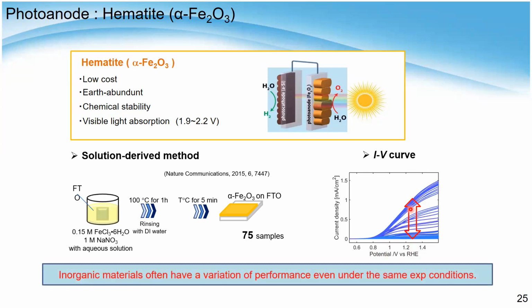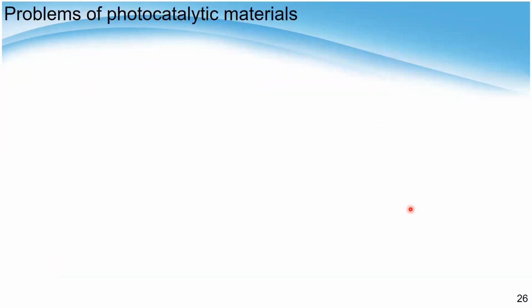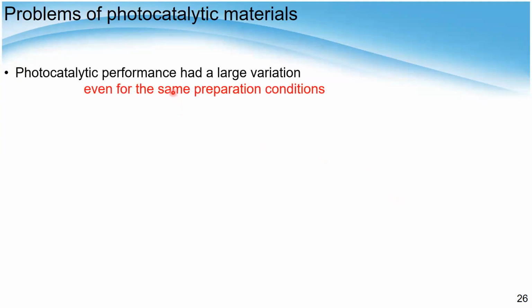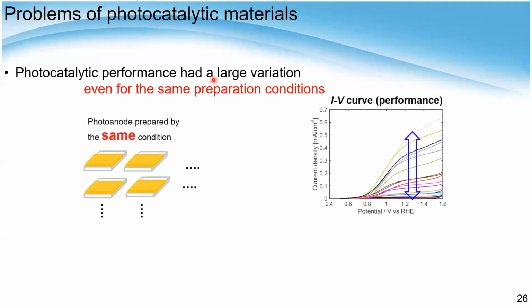But as you see, inorganic materials often have a variation of performance even under the same experimental condition. So what I mean is that the photocatalytic performance had a large variation even for the same preparation conditions. We prepared the hematite materials under totally the same experimental condition, and this is the performance. This curve is called the IV curve, potential versus current, and at 1.23 volt, which is the potential for water oxidation, this value is the target value of Y.